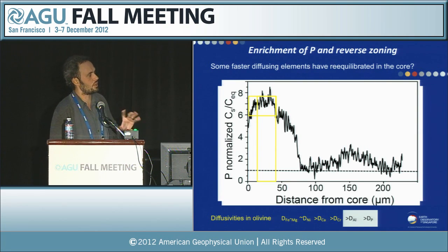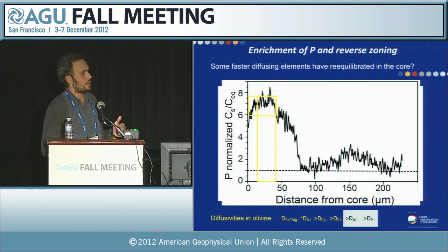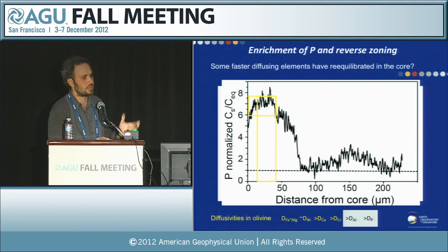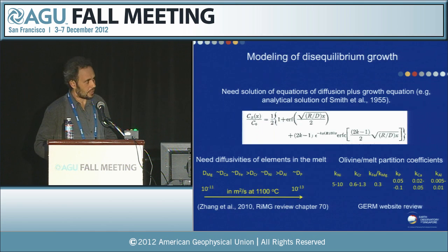First, the phosphorus. How one can think about it, I thought about it by using some equations for disequilibrium growth, and the first thing one needs to do is to normalize. So you have to find how much in disequilibrium it is, and what I did is I took the flat or low phosphorus zones as my equilibrium values. I assume that here the crystal was growing at equilibrium, and then normalized to the rest. This is now a reverse plot, but you have here the high phosphorus zone. This high phosphorus zone was enriched 7 times its equilibrium concentration.